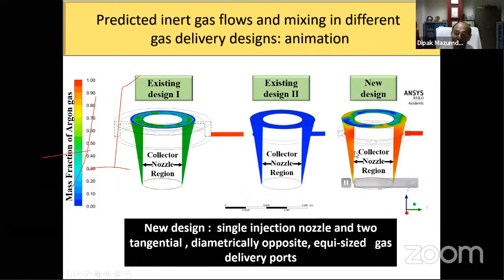On the other hand, if you look at the new designs, of course, at this particular surface, the air is present, so that's why you see some blue region, but the bulk of that annular space between the collector nozzle as well as the shroud is red, which essentially indicates that this is filled with argon. So whatever we have found out computationally and experimentally by water modeling can be depicted very nicely through this animation. And the summary of it